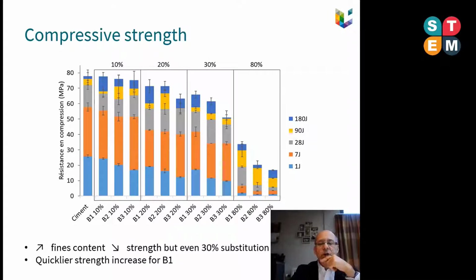The results clearly show that increasing the fine contents and decreasing the cement content will decrease the strength of the material. However, even with 30% of substitution, compressive strength remains interesting. That means that we can find regular applications, specifically for B2, corresponding to a classical dimension for fine particles. We obtain still more than 60 megapascal as compressive strength after 90 to 180 days, which is interesting and corresponding to classical application in the concrete industry.